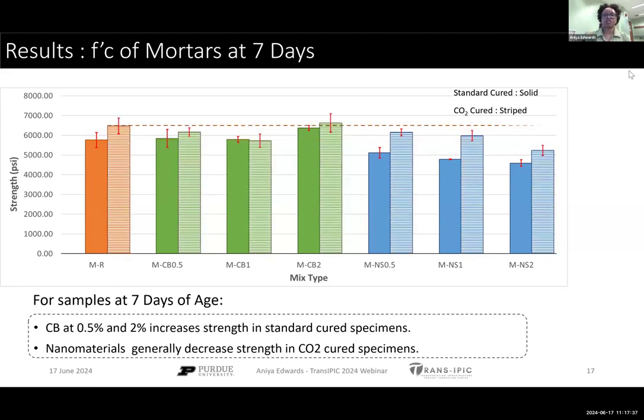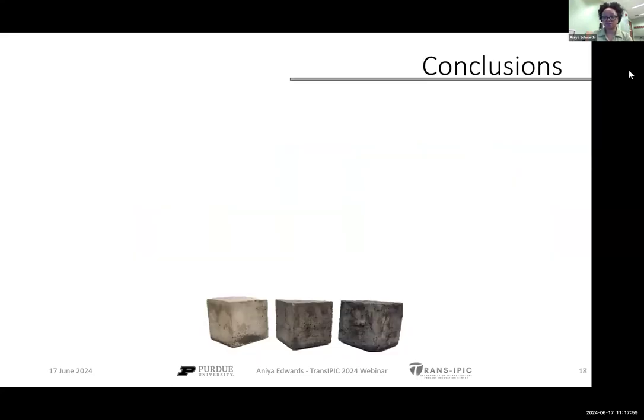And then for our CO2 cured samples, we're seeing that almost all of our nano-added specimens reduce the 7-day strength. The only one that exceeds the strength of the reference is carbon black at 2%. So we can say that carbon black at 0.5 and 2% does increase the strength, but nanomaterials generally decrease the strength, particularly in CO2 cured specimens.